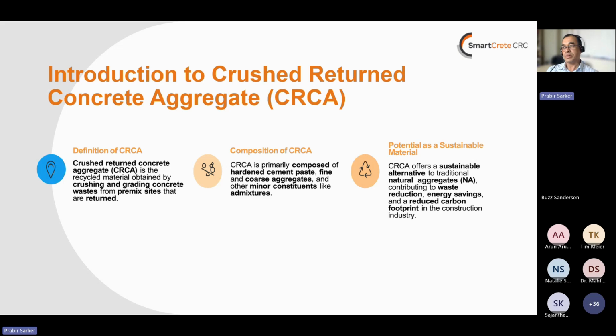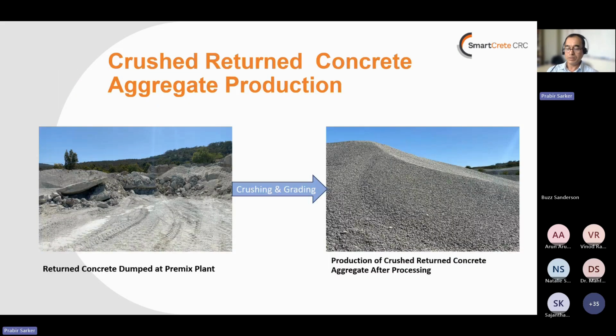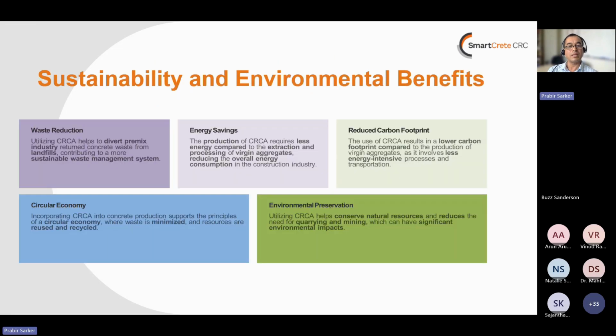The other difference is that this concrete is relatively young as compared to the C&D waste concrete aggregate. And this concrete, as we have seen, comes back to the plant and is just dumped at the site, so it doesn't go through proper compaction and just normal curing, no special curing effort is employed. So these are the differences between the crushed return concrete aggregate and C&D waste aggregate. That can make some difference in the properties of the aggregate and eventually some difference in the properties of the concrete made using this. So this is the process: dumped concrete is crushed and made into aggregate.